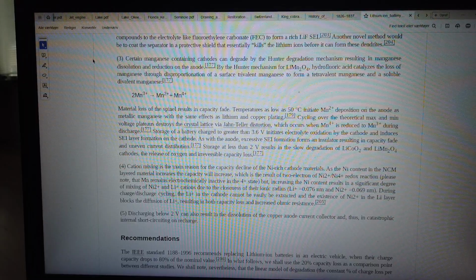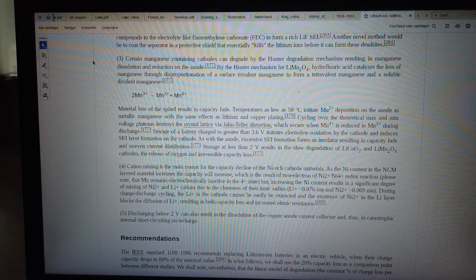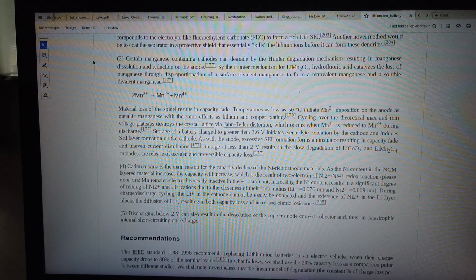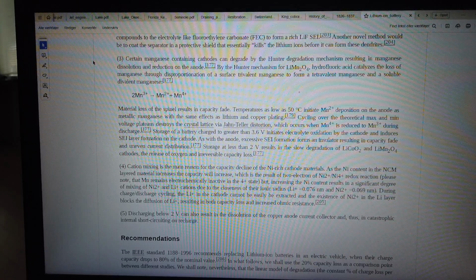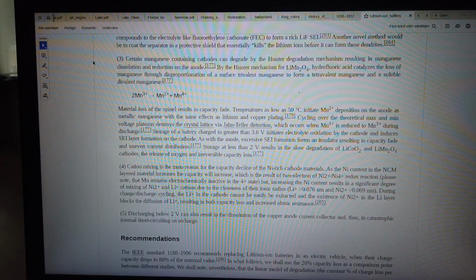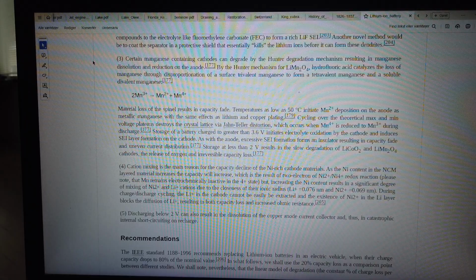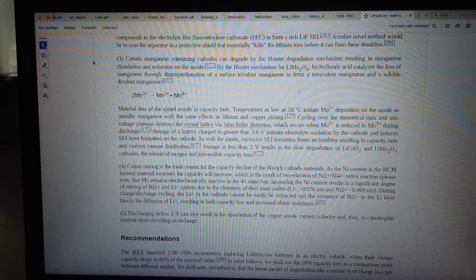3. Certain manganese-containing cathodes can degrade by the Hunter degradation mechanism, resulting in manganese dissolution and reduction on the anode. By the Hunter mechanism for LiMn2O4, hydrofluoric acid catalyzes the loss of manganese through disproportionation of a surface trivalent manganese to form a tetravalent manganese and a soluble divalent manganese: 2Mn3+ → Mn2+ + Mn4+. Material loss of the spinel results in capacity fade.